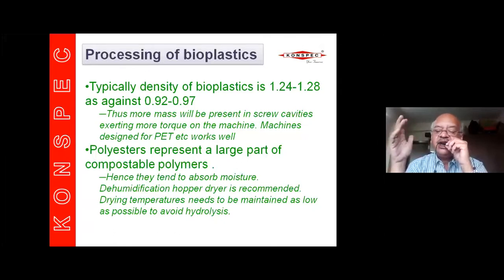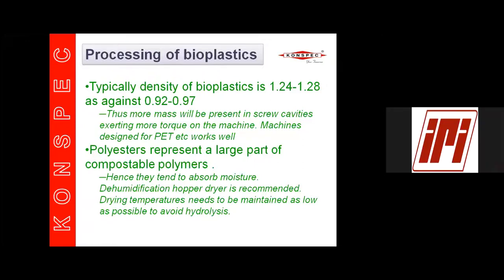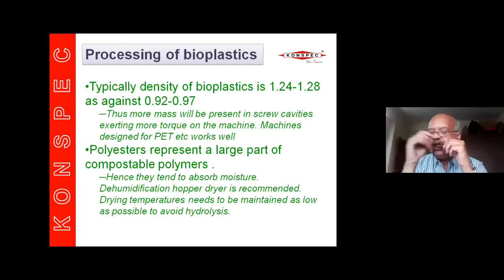So when we are drying the material, the moisture is going out, but before it goes out, it is already breaking the polymer because of heat. So please ensure that the hopper dryer is set at a very low temperature, as low as possible, to avoid the moisture absorption. Third is, whenever the raw material comes to our factories, please ensure that we open it as and when needed and not open all the bags and start planning for the whole day. Number one. Number two, any leftover material should be packed back into bags after drying and then sealed before we use it again. Let me tell you a small example.